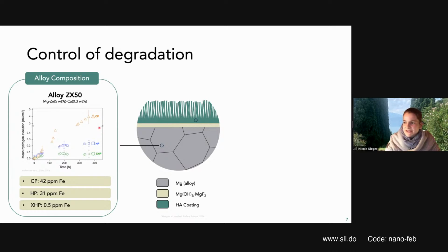And what you see is that we have a lot faster degradation for conventional purity, which contains some ppm of iron ions. Now, it was found that even really low concentrations of impurities will make the degradation of these magnesium parts go a lot faster. And if we have really high purity, we can control the rate to a really low level, which is actually even too slow, and some alloys will have to be added to increase, again, the degradation speed.